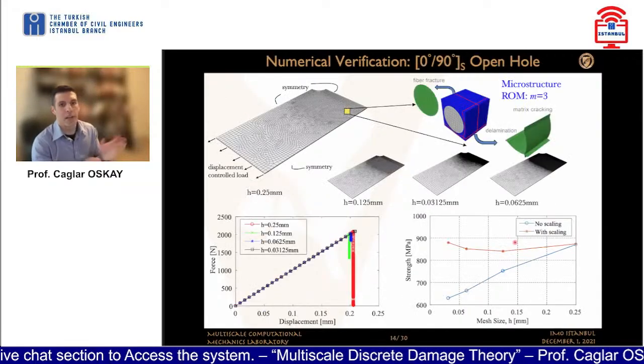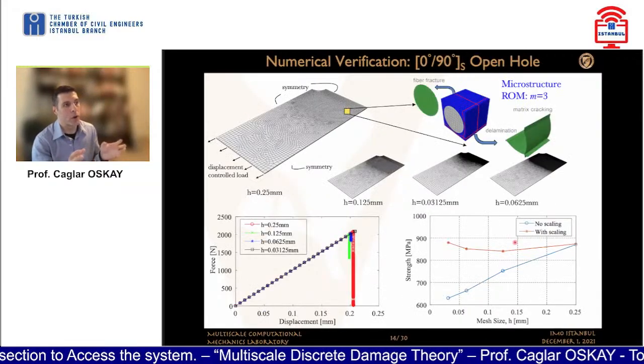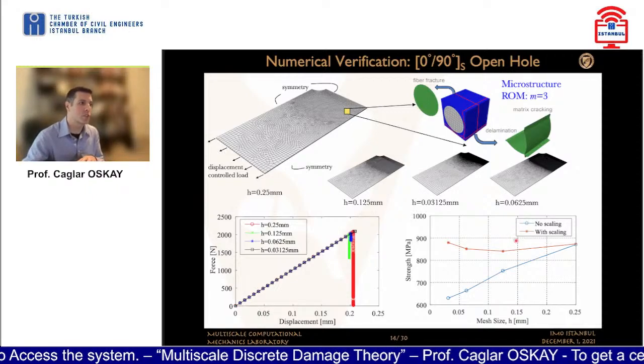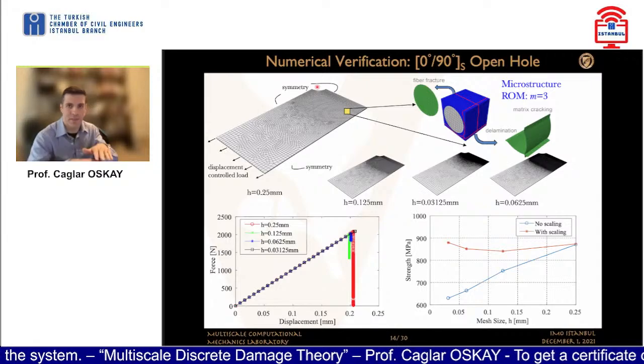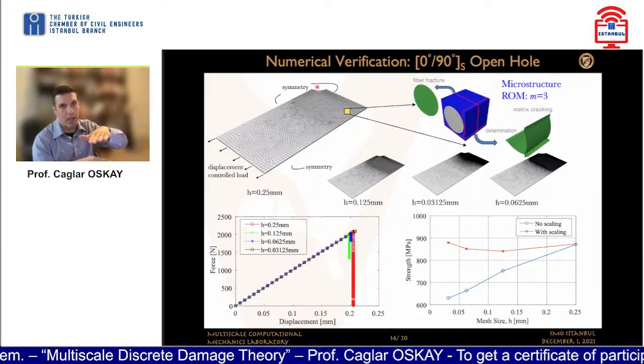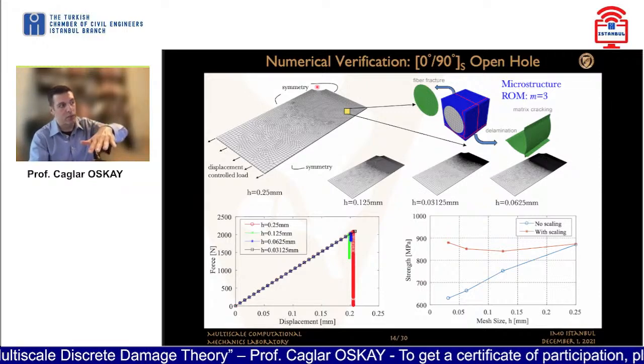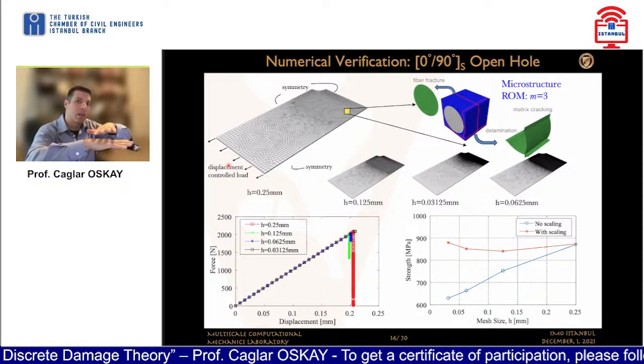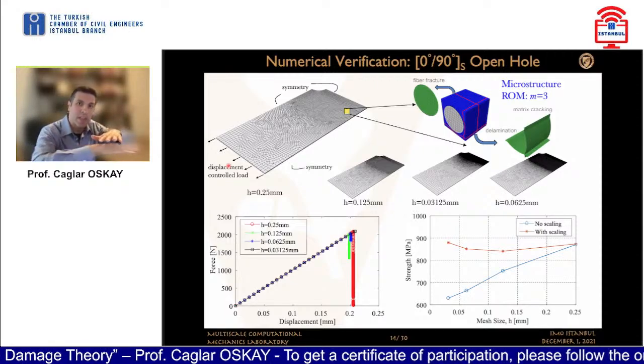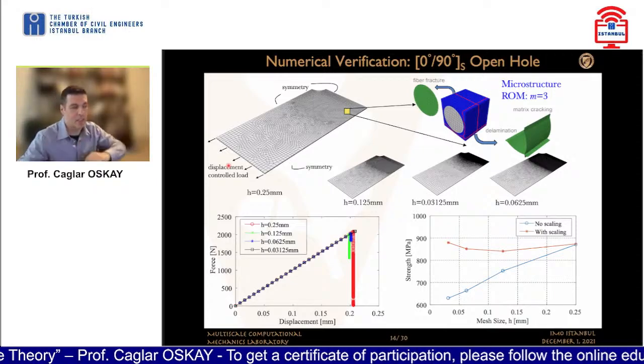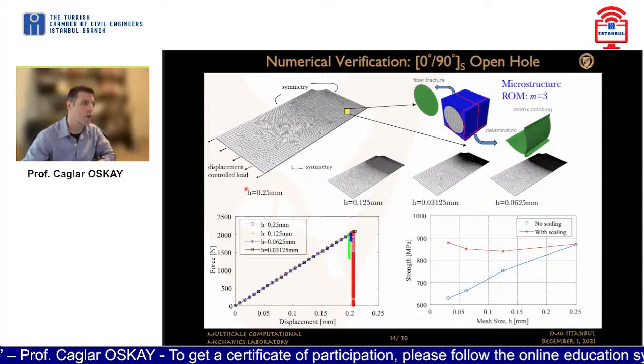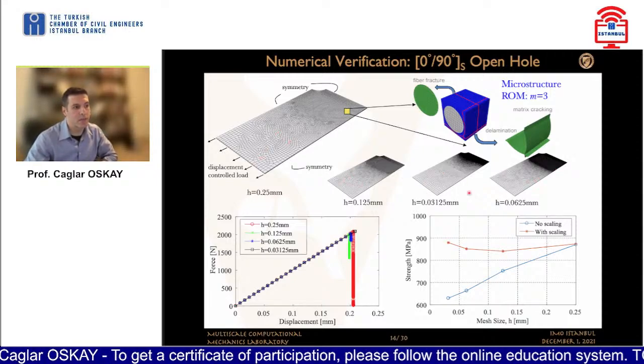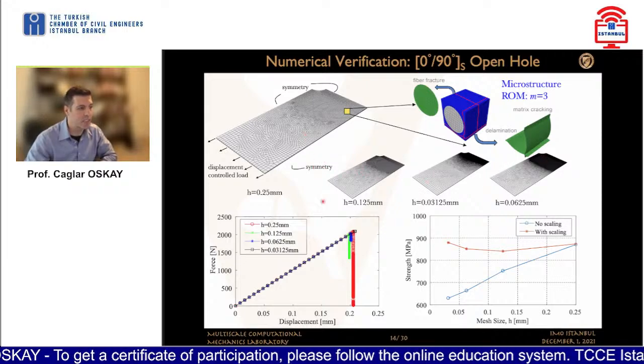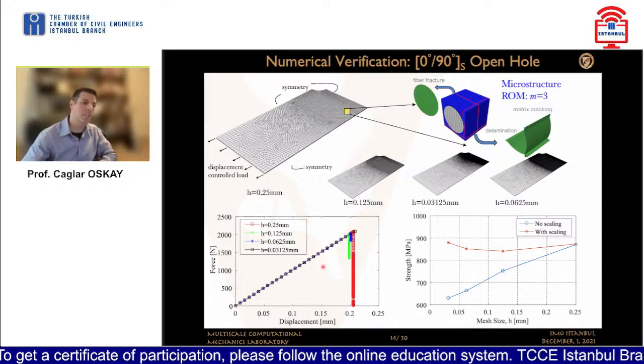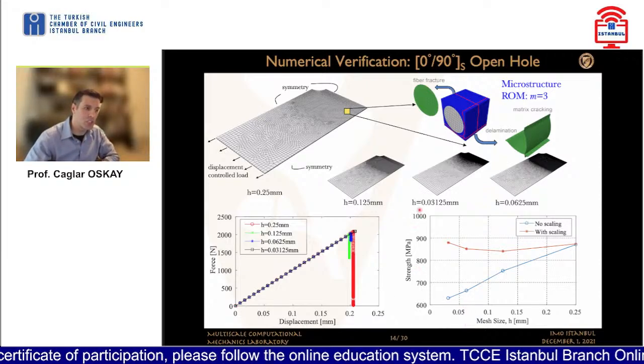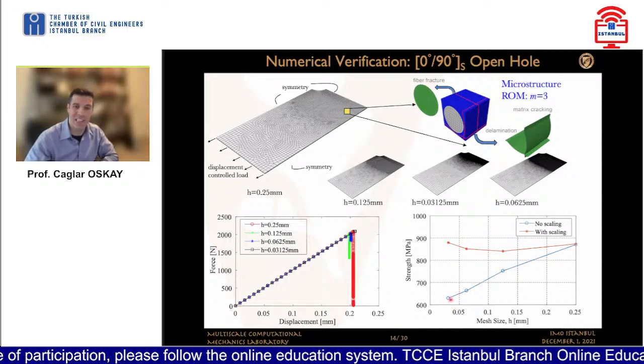So an example. In this case, we're looking at an open hole specimen with a 0/90 configuration. An open hole specimen means that you have a hole in the middle of a specimen. It's a flat specimen. 0/90 indicates that the zero layer has fibers that are oriented along the direction of the loading, and the 90 plies are where the fibers are oriented perpendicular to the direction of the loading. So they're basically cross-ply laminates, is what we call them. And we are running simulations with various different mesh densities, quite intense mesh densities. If you don't use the regularization approach in the MDDT, you see a clear variation of the strength prediction as a function of the mesh size. It's more or less a linear behavior.